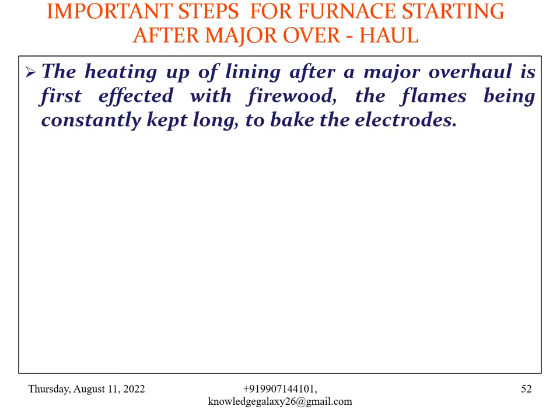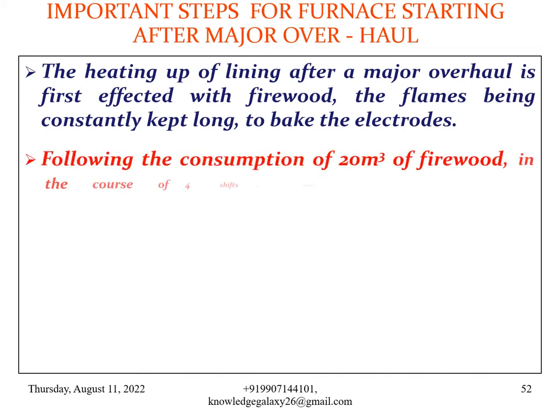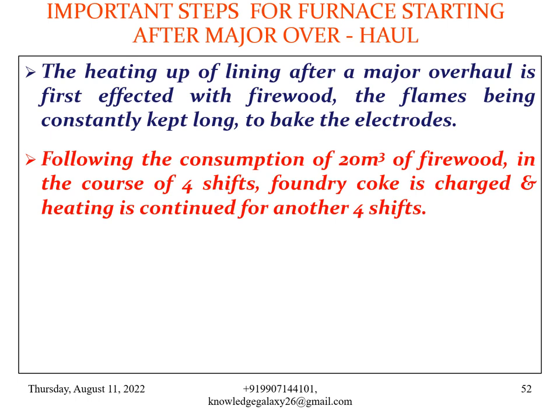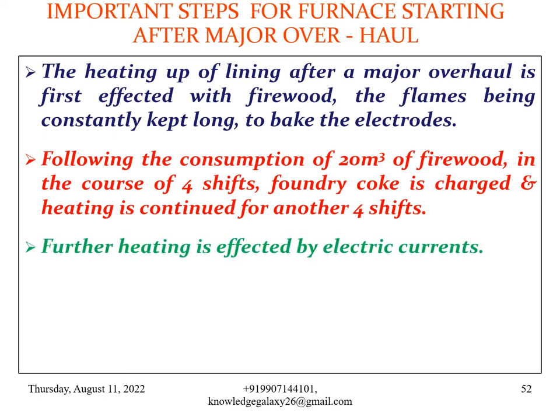The heating up of lining after a major overhaul is first effected with firewood, the flames being constantly kept long to bake the electrodes. Following the consumption of 20 cubic meter of firewood, in the course of 4 shifts, foundry coke is charged and heating is continued for another 4 shifts. Further heating is effected by electric currents.